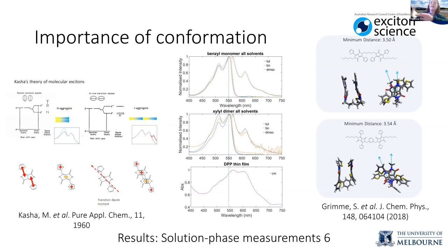They can either be coplanar, so one on top of the other. And in this case, this leads to a higher energy absorption peak called an H aggregate peak, or they can be head-on or slip stacked. This leads to a low energy peak. And what we've found is that there's always this low energy peak in examples where you see singlet fission in DPP. So it might be indicating that that particular structure is quite important in order to have this process occur. You can see here that in the monomers and the dimers, we don't see a low energy peak. So it's more likely to be in this H aggregate configuration compared to in films and nanoparticles.